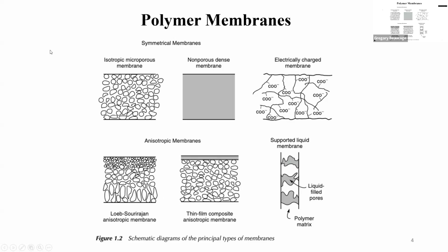And this is one of the first things that the UCLA guys figured out. They made a bunch of membranes, and half of them were great and half of them were terrible. And it took them like 2 years to figure out that one side was rough, one side was smooth. That's what I mean by it's an empirical process. Literally took them 2 years to figure out. And then after that, they could produce perfect membranes all the time. It's just like the major discovery.